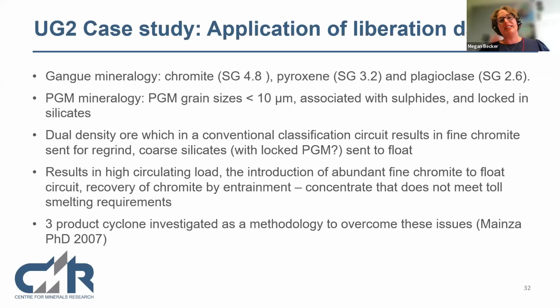So let's just give a bit of context to the UG2. The UG2 is a chromitite rock ore in South Africa. And in it, the 3 dominant minerals are chromite, between 40 to 60% depending on the mining cut, and then pyroxene and plagioclase. And I've given you the densities. You can see chromite's close to 5, pyroxene and plagioclase more like 3. So we already see this is a dual density ore, and it's going to have potential problems for classification. In this platinum group element ore, the PGM grades are obviously a few grams per ton, but the grain sizes are generally all less than 10 microns. And some of these PGMs are associated with sulfides, and some of them are locked in silicates.